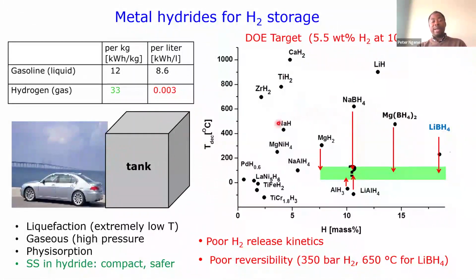And already what you can see here is the DOE target for the type of material that can be used. So you need to store about 5.5% hydrogen at this moderate condition, about 100 to 150 degrees centigrade. However, if you look at most of the metal hydrides, they either store a very small amount of hydrogen in this temperature window, or they are the ones that contain a very high amount of hydrogen, like sodium borohydride, magnesium borohydride, lithium borohydride. This is a very interesting one because it has about 18% hydrogen if you go full decomposition. However, you can see that the temperature window at which it can release the hydrogen is quite high, so it's not doable. We cannot use this.